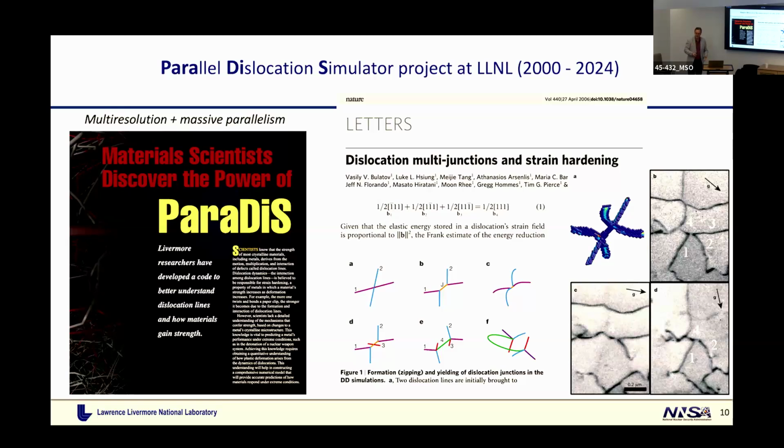So we designed an experiment, ran a deformation experiment, and thinned this into TEM transparent films. I was bringing pizza to our TEM microscopist, and he found that out of 35 configurations suspicious for the presence of such 4 nodes, a good fraction, about 30%, were correct quadruple nodes. And they have a very specific signature in TEM contrast. So we identified that these are there. It was very pleasing. You get something from simulation or theory, and you predict it, and it is there. So it was not just a computational engine. It was also a research tool.